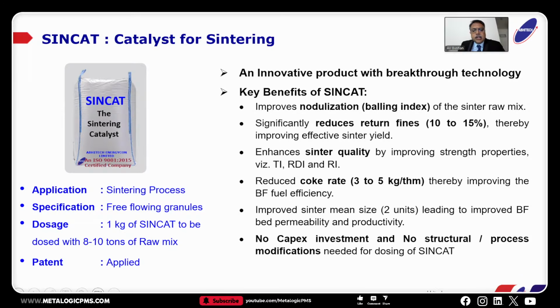in the sinter process. So this product improves the nodulization or the balling index of the sinter mix. It also significantly reduces the BF return fines, the internal fines as well as the blast furnace return fines, and therefore overall increases the net sinter yield. It also enhances sinter quality by improving the strength properties like TI, RDI and RI. And these in turn lead to efficiency improvements in the blast furnace in terms of coke rate reduction as well as an increase in hot metal production. Next, please.